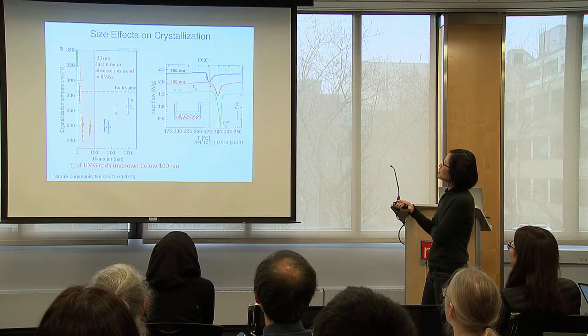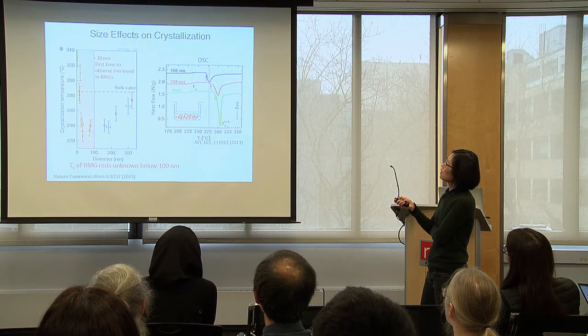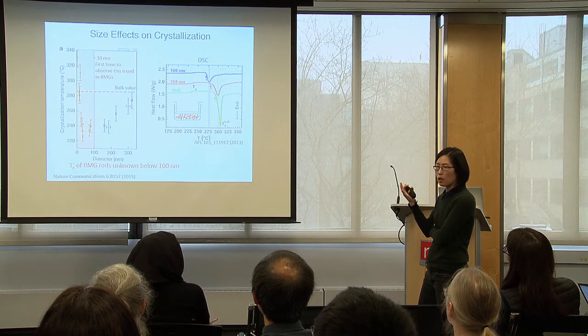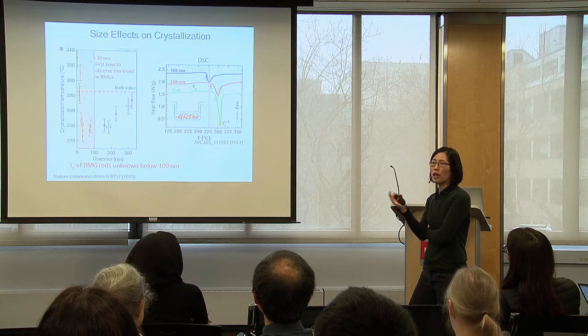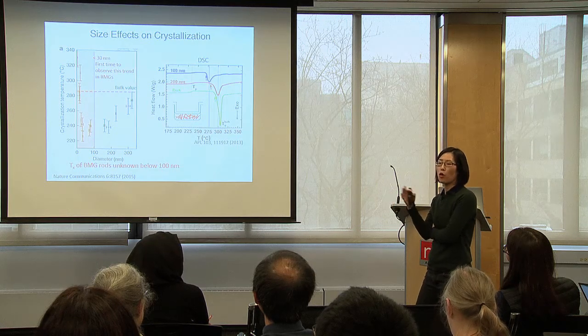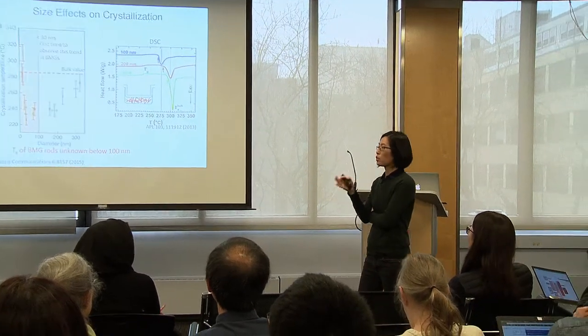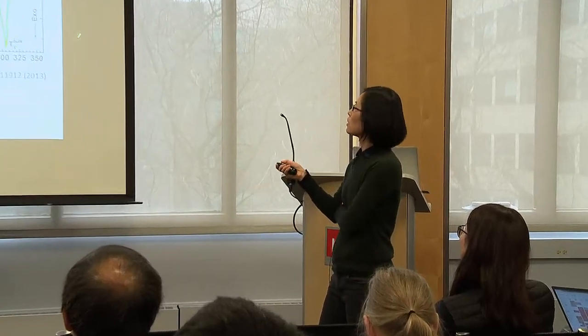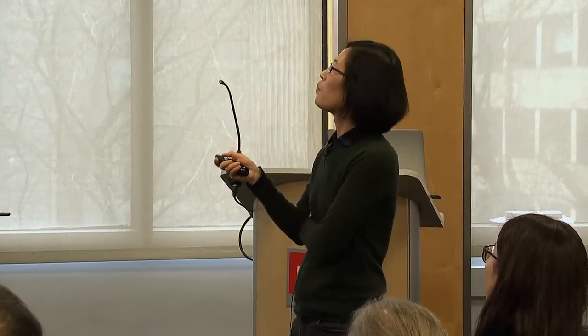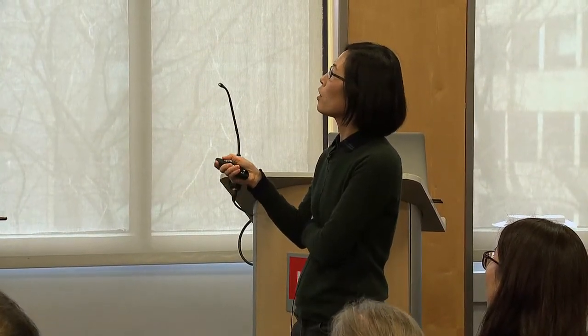With these results, it's reasonable to expect that crystallization is easier to happen, and then you would think maybe that's because you have more surface, and heterogeneous nucleation is easier than homogeneous nucleation, because the nucleation barrier is lower. So this trend makes sense. Now what we see is that if you go further below, then the trend reverses. So why is that?